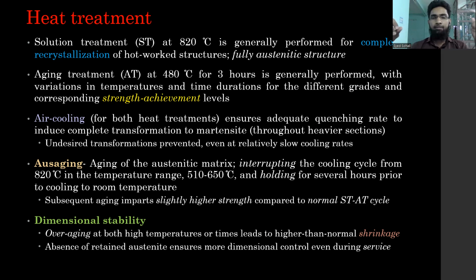That is the principle. Another thing is the extremely low percentage of carbon. Because of this advantage, a protective atmosphere is not required during annealing or even aging, and the cooling rate is not critical for martensite. The cooling rate is not critical; it doesn't need to be controlled. So you have this advantage as well. Air cooling is done, but you don't have to control the air cooling, for both solution treatment